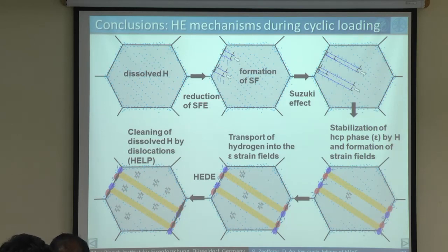And the combination of all our techniques allowed us to prove this, except a direct proof that hydrogen is really there. And that is missing, of course. Hydrogen is so difficult to see. Can we do it? In principle, yes, but in practice, not yet. In principle, yes, because hydrogen gives a signal. In practice, not, because in an atom probe you have hydrogen everywhere, and the hydrogen is so mobile it can go everywhere.